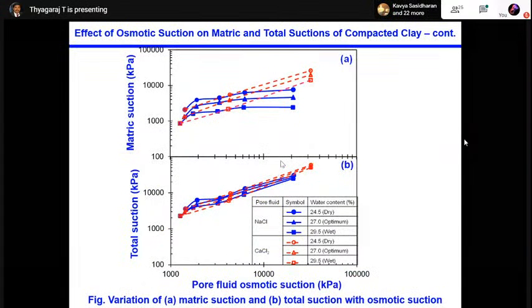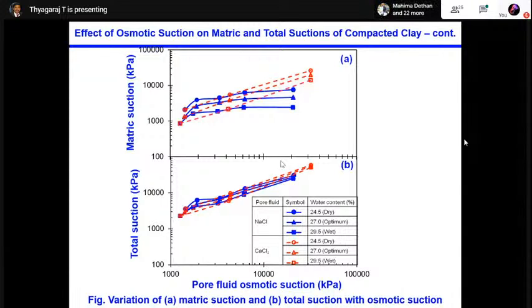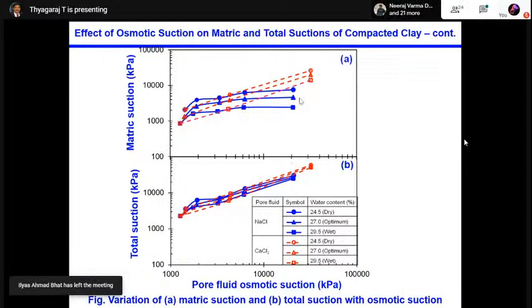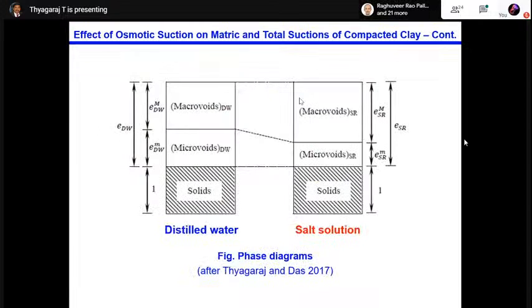For that reason, since the matric suction is a characteristic of the macropore and the degree of saturation of the macropore, with increase in pore fluid suction, osmotic matric suction increases. So far, there was an understanding that it will not increase, but this was published in Geotechnique in 2015. And then, since it has an effect on the suction components, we thought it will also have an effect on the hydraulic conductivity behavior, and also it should affect the leachate and so on.